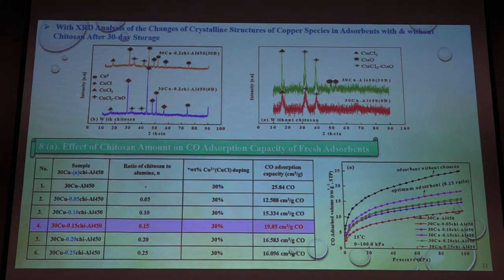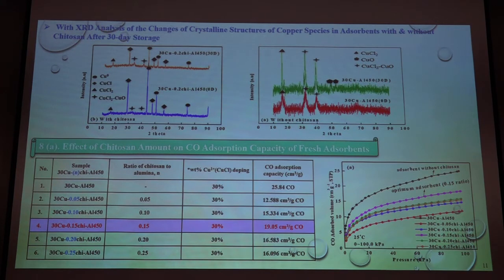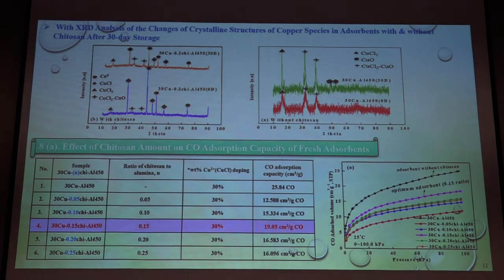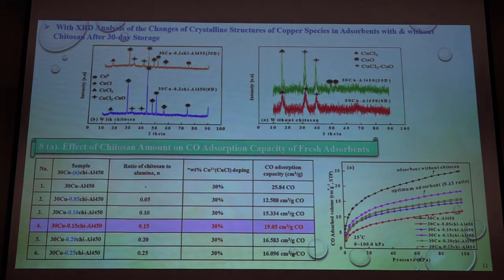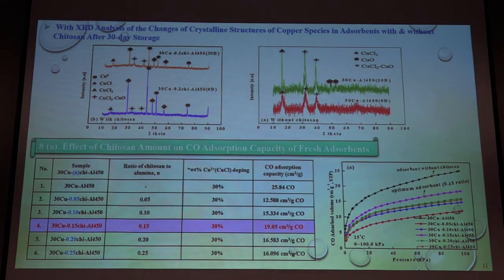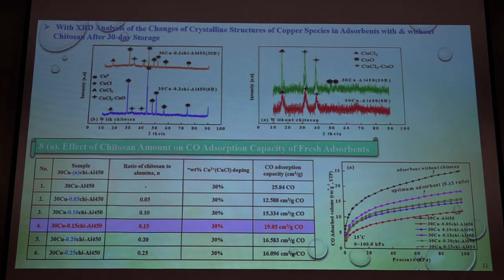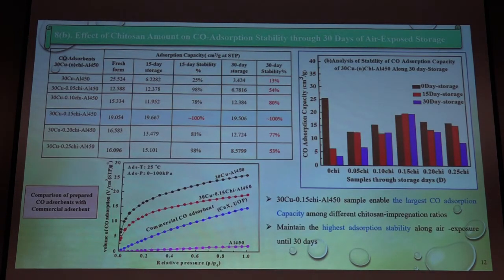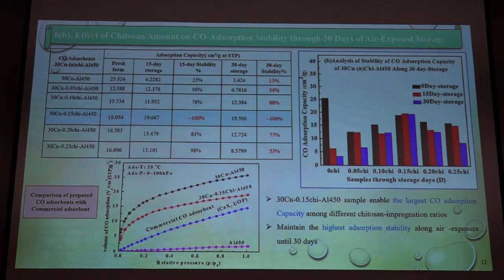So by these analytic results and the isotherm results, I can confirm that the chitosan definitely has a stabilization activity for CuCl-based CO absorbent to get a stable CO absorption capacity. This time, I want to know the effect of the chitosan amount on the stabilization of the CO absorption capacity. Among various proportions, we can see that the 0.15 chitosan sample gives the highest CO absorption capacity as fresh. Moreover, even after the 30 days of exposure, it can still maintain its initial absorption capacity.